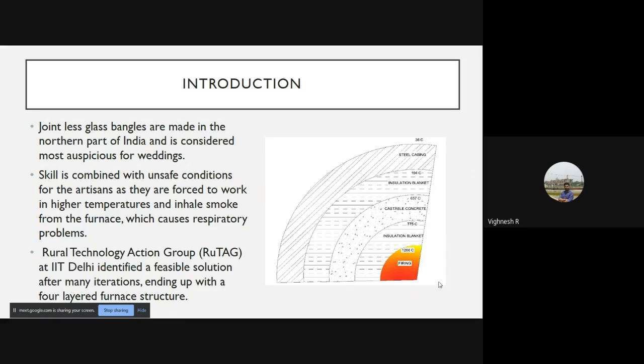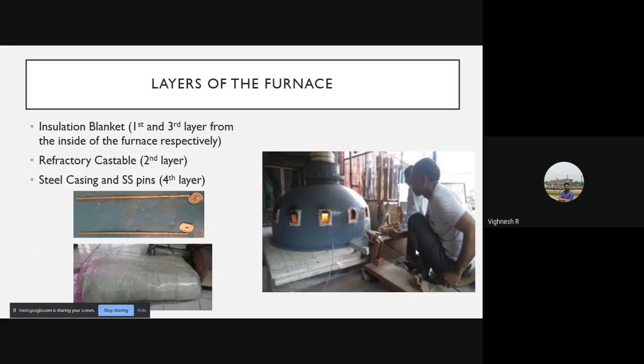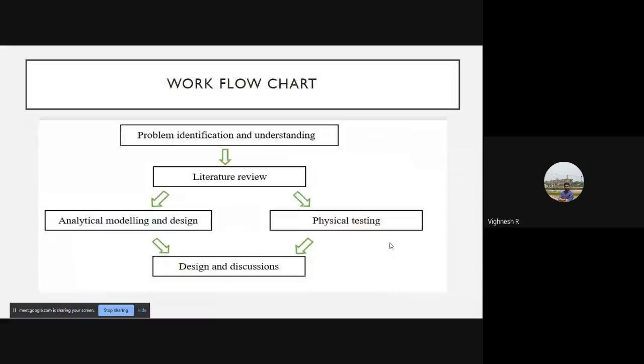This firing will have a very massive temperature. If we don't give a very good insulation or a refractory castable concrete to resist this high temperature from coming out of the furnace, then it's very difficult for the artisans to make their art. So that's what we wanted to do. The flow chart which I wanted to present was like, we went to a couple of sites before this, and we decided how to select the materials based upon what was built before.